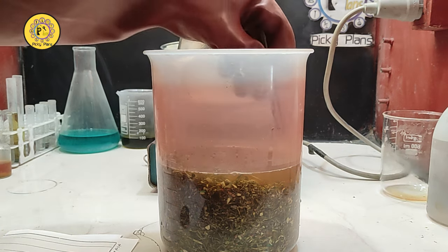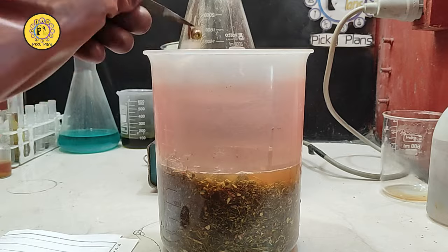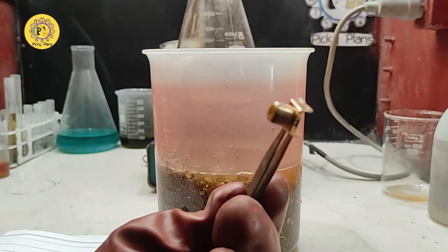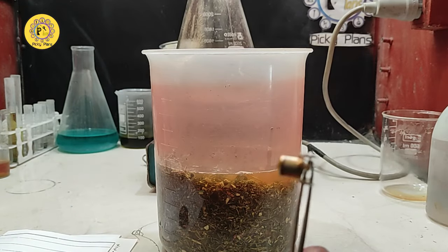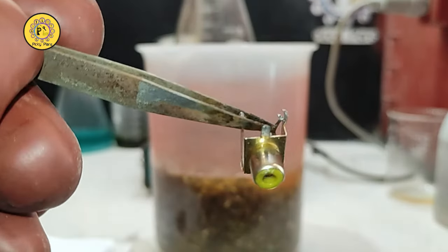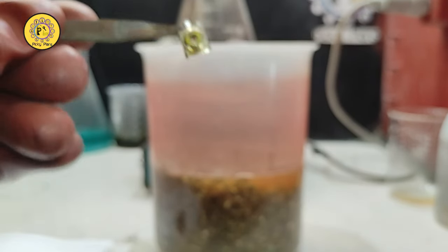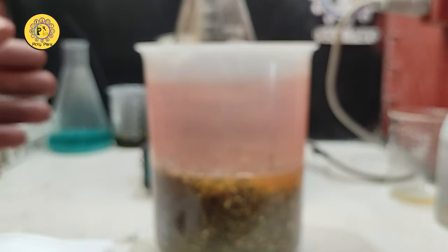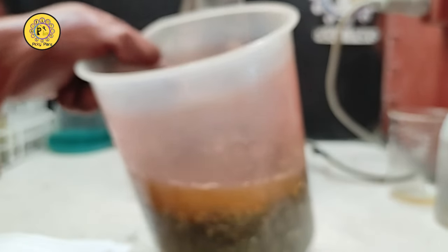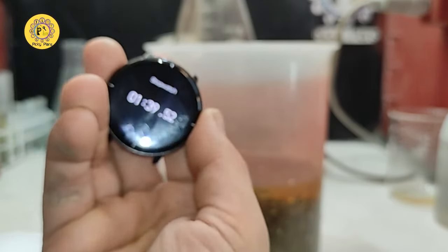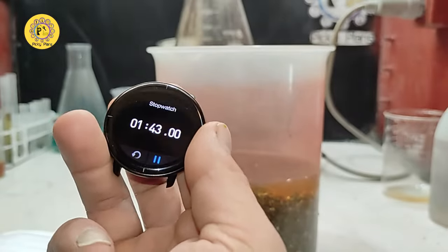Also, as the indicator, there was a gold plating socket here, which has been almost leached completely. Let's show you. The golden layer is gone. Probably this is happening to the majority of pins inside this beaker. And as I can see, there are no more pins with gold plating on the top, at least on the top. And it's not being 2 minutes though.